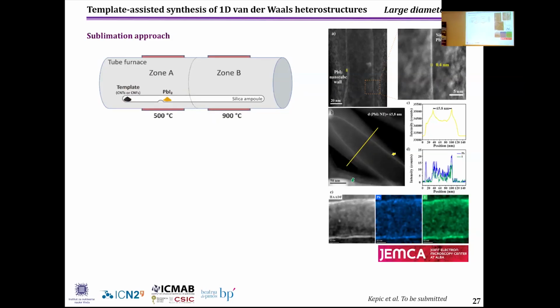One advantage of the sublimation approach is that the protocol is clean, because when we mix in the molten phase approach, we mix the materials together. So usually the removal of external material is required. In this case, these samples were practically clean under the characterization we performed. And we also confirmed that we have nanotubes, inorganic nanotubes, inside the fibers.